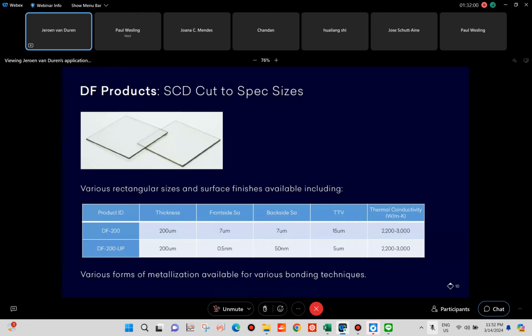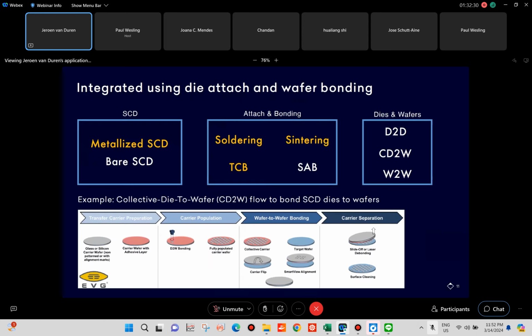We also have the DF200 ultra polished, same thickness, 200 microns, with a front side roughness less than 5 angstroms, so 0.5 nanometers. Backside 50 nanometers. TTV is tighter. It's 5 micrometers, and also there we offer both 2,200 watts per meter Kelvin and 3,000 watts per meter Kelvin. In addition, various forms of metallization are available for various bonding techniques. Regarding the integration, diamond can be integrated using die attach and wafer bonding techniques. So the diamond can be metallized, or it can be used as bare diamond.